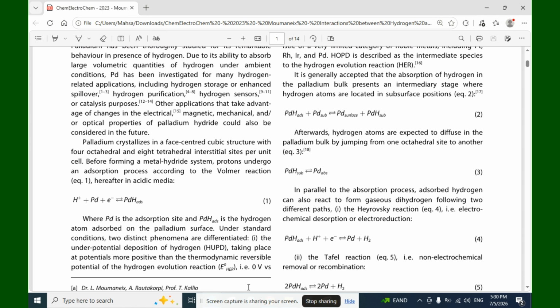Palladium crystallizes in a face-centered cubic structure with four octahedral and eight tetrahedral interstitial sites per unit cell. Before forming a metal hydride system, protons undergo an adsorption process according to the Volmer reaction, equation 1. Hereafter, in acidic media, H+ + Pd + e- ⇌ Pd-H_ads, where Pd is the adsorption site and Pd-H_ads is a hydrogen atom adsorbed on the palladium surface.